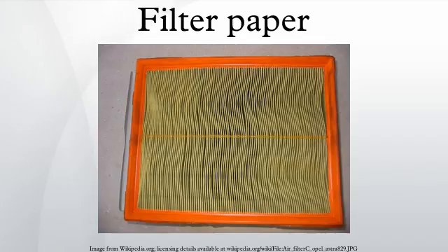A paper for air filters needs to be very porous and have a weight of 100 to 200 grams per meter squared. Normally particularly long fibrous pulp that is mercerized is used to get these properties. The paper is normally impregnated to improve the resistance to moisture. Some heavy-duty qualities are made to be rinsed and thereby extend the life of the filter.